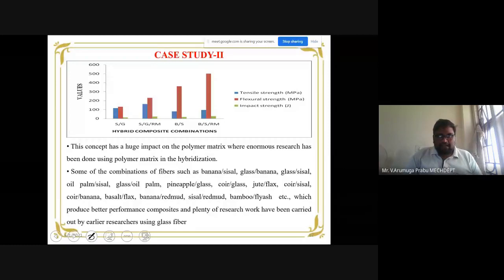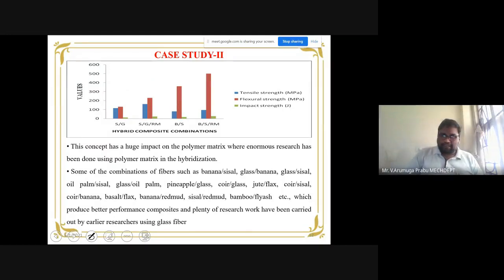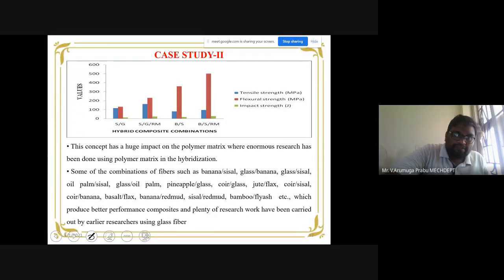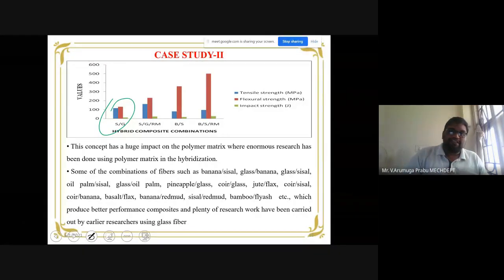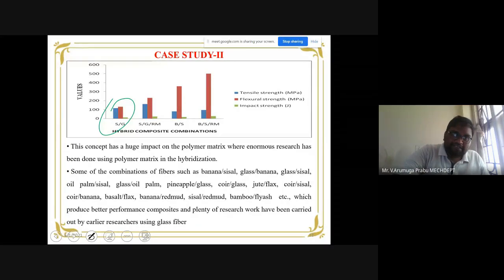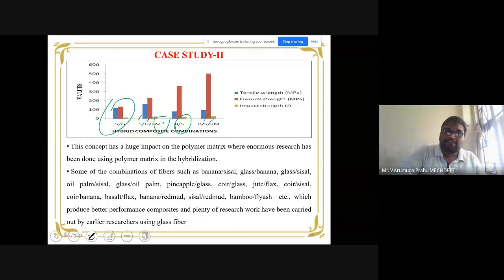Okay. And this is a small comparison about another kind of hybrid composite produced using industrial waste along with two fibers. See, these results are for one fiber along with the industrial waste filler and matrix. Here you notice two fibers. The first one is the sisal and glass combination. One natural, one synthetic is taken. Then this is compared with sisal, glass and RM, which is red mud, the industrial waste filler. In the same way, like sisal glass, BS is the combination of banana and sisal, both natural fibers. So this banana sisal natural fiber composite is compared with the banana sisal red mud composite.